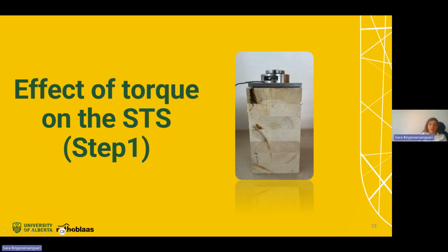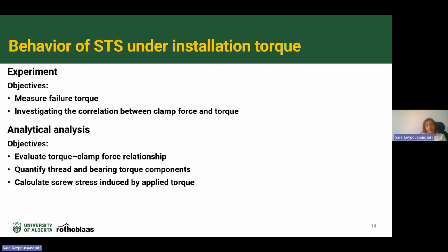So in order to find the stress on self-tapping screws, we started with dry condition and step 1. The objective of this step was measuring the failure torque and investigating the correlation between the clamp force and torque. Also, we tried to focus on the analytical model as well, because we know that there are some equations and formulas available for bolts and nuts, and also it was used for lag screws in wood, but we were not sure whether we can use that for self-tapping screws or not. So we did some tests in order to make sure that they are applicable for self-tapping screws as well.